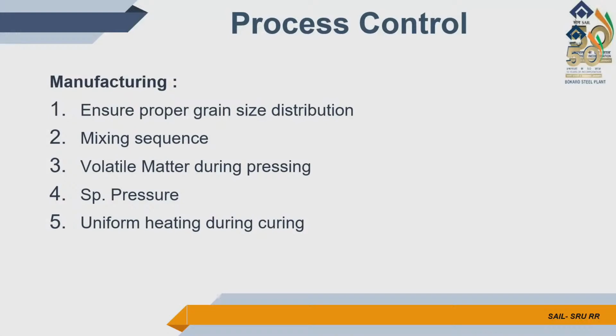So things that we did at our end is we made many different compositions, changed different size distributions, and had an optimum size distribution made, which gives the best properties. We had experimented many mixing sequences, and we had an optimum sequence: what to add after which, and how much time you mix. So we had a good mixing sequence.